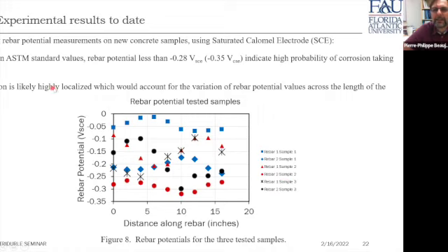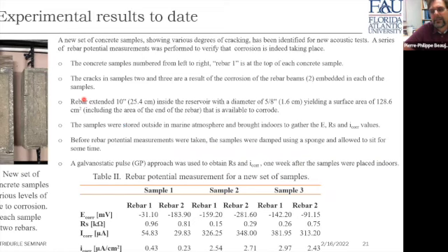And corrosion is likely to be highly localized, which would account for the variation of the rebar potential values along the length of the rebar over here. So you notice that the potential value changes as we actually change the length or the distance along the rebar, I should say, which actually is due to the fact that we have highly localized corrosion. Now, I would mention for these 2 slides, this is predominantly the work performed with the help of Dr. Preswell, and this is his field of specialty.